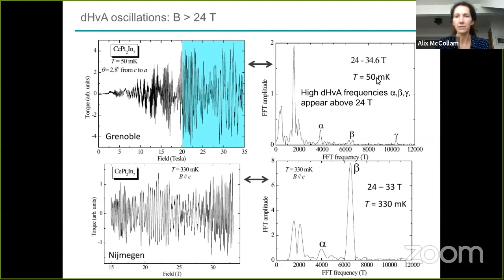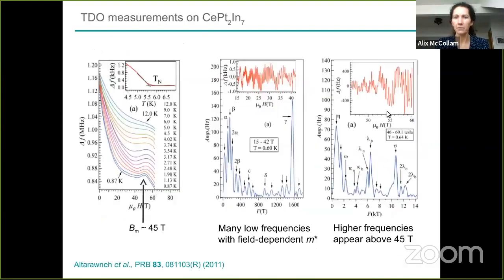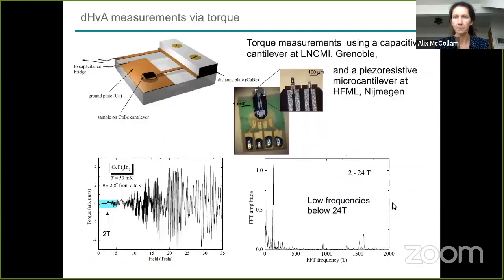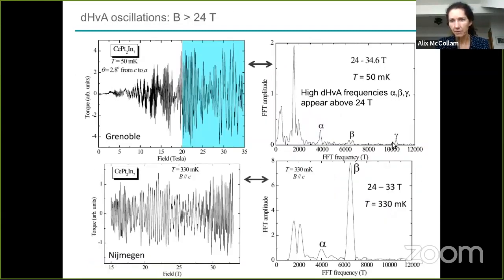So above 24 Tesla, we see the emergence of these high frequencies, and these are the frequencies that correspond to the high frequencies that emerge here. If you look at these kiloteslas, this is 6, 12, etc. This is not quite 12, but these 6 and 4 kilotesla frequencies are the ones that emerge. But we see them not above 45 Tesla, but above 24 Tesla. So at a much lower field than they were observed in the previous work.